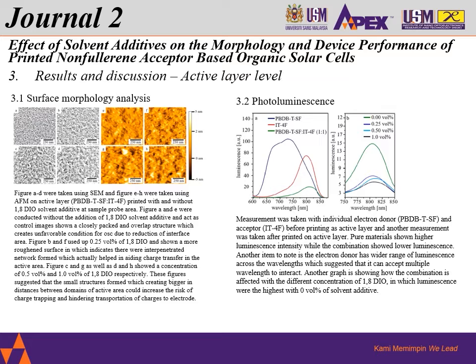And then increasing the concentration of DIO itself, you can see that the surface is slightly roughened, and actually this indicates that an interpenetrated network formed, helping in aiding the charge transfer in the active area. So this is favorable.